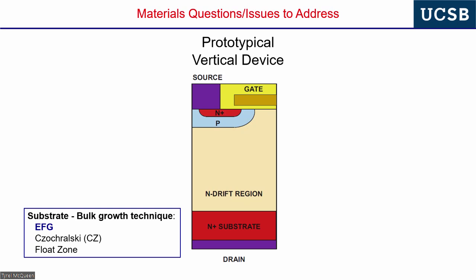and then on many aspects of the electronics with Umesh Mishra at UCSB from the nascent days of the field. And what we did not have in gallium nitride at the time was a native substrate. So we grew on foreign substrates. And the foreign substrate of choice is sapphire or silicon carbide, and it leads to a very dislocated semiconductor. And my formal training is in transmission electron microscopy and dislocations. So it's been extremely lucrative for me because we have this defective semiconductor and I know a lot about dislocations. It's been great. But it so slowed the progress in the field because even though many folks wouldn't admit it, we were always facing materials quality issues because of the dislocations.